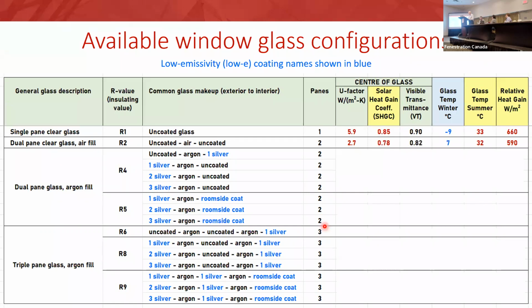So if we look at our 2 existing glass products, we see that the double glazing made a big difference. It cut your U factor in half, cut your heat loss in half. It brought your glass temperature up from -9 to +7. Granted, this is under NFRC winter conditions, so it's -18 outside, +21 inside. And it's got quite a lot of solar heat gain. That double pane unit has almost the solar heat gain of a single pane of glass. So great for solar heat gain, but not if you're overheating.